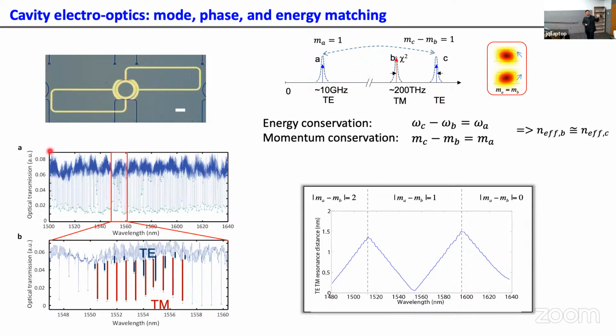However, the mode splitting is normally on the order of 100 gigahertz. So we make a little bit of a compromise on this coupling. To reduce the TE-TM coupling, we make the TE and TM azimuthal numbers mismatched by 1 or 2. In this case, we use 1. And here the mode splitting between the TE and TM modes becomes around 8 to 10 gigahertz, and that falls into the microwave resonator frequency range. Now we can get efficient microwave to optical conversion.